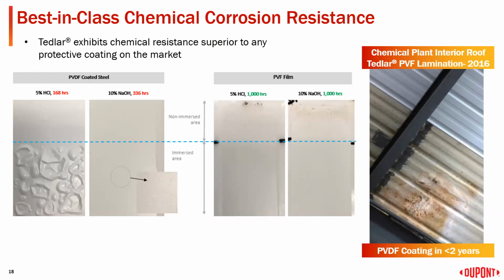So here's another really nasty one. So we're looking at chemical plants, right? So we're looking at industrial applications where there might be some corrosive gases or exposure to other nasty elements. And we're looking at a couple chemical tests that we do where we basically dip a painted or laminated panel into chemicals. The PVDF coated steel that you're seeing, that's what we did our test on the left, it's starting to bubble right away pretty quickly in less than 200 hours. And then the PVF film, we've got 2 of our strongest chemical solutions for 1,000 hours, no reaction whatsoever. And it can sit for quite a bit longer than that as well.